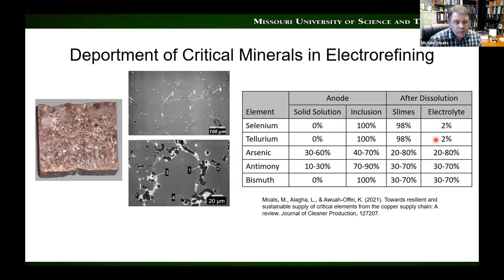And so you can see for the group 15 elements, the arsenic, antimony, and bismuth, that there's a whole range of what happens. In fact, if you go back way early in my slides, one of the projects we have funded by several of the copper refineries is to understand better these group 15 elements because they're problematic. Why are they problematic? Because they can produce what are called floating slimes. Floating slimes are particles that are colloidal. They float across between the anode and the cathode, and they get encapsulated in the cathode and make off-spec copper, lead to short circuits, and cause low current efficiency. So the control of arsenic, antimony, and bismuth in the anode and the electrolyte is really critical for an electrorefinery. It's been like this since time eternal, since we invented the process in the 1850s.